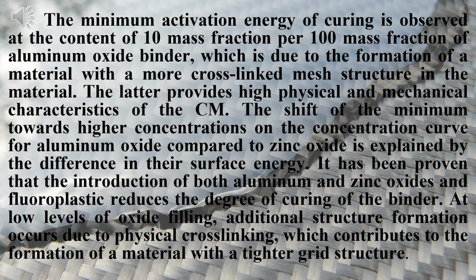The shift of the minimum toward higher concentration on the concentration curve for aluminum oxide compared to zinc oxide is explained by the difference of their surface energy. It has been proven that the introduction of both aluminum and zinc oxide into fluoroplastic reduces the degree of curing of the binder. At low levels of oxide filling, additional structure formation occurs due to physical cross-linking, which contributes to the formation of a material with a tighter grid structure.